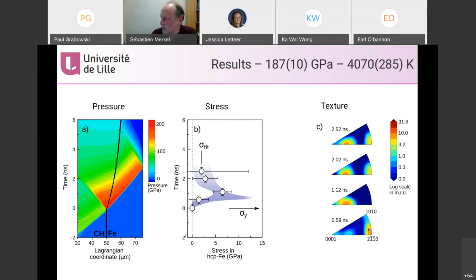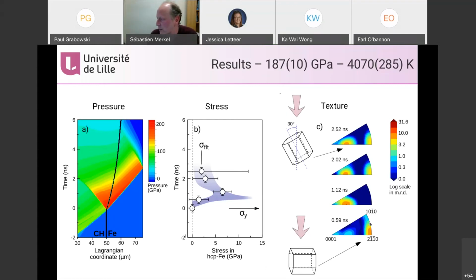And then as the shock front is moving through the sample, the texture switches to 30 degrees away from 001. I have drawings here. If you're not very comfortable with textures, this is what happens. When you form HCP iron from BCC in the shock, you get a texture, grain orientations with the C-axis perpendicular to the shock direction.